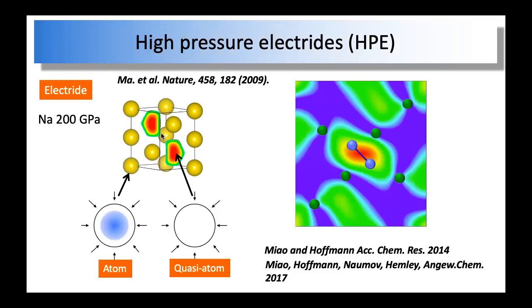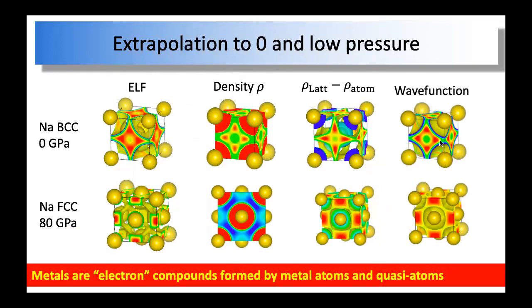It's just like oxide or sulfide, chloride, right? So of course, the valence orbitals are fully occupied, right? But if you look at this, they are not fully occupied. They are partially occupied. And if you calculate the values, it is not very small. It's 1/4 or 1/2 of what we can see from the electride. So the occupation is not so small. However, it's partially occupied, and of course it is partially occupied because it's a metal, right?